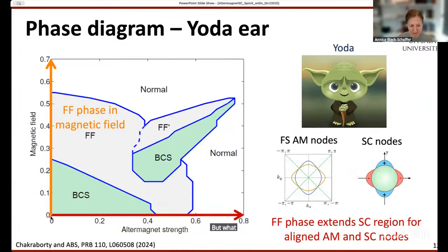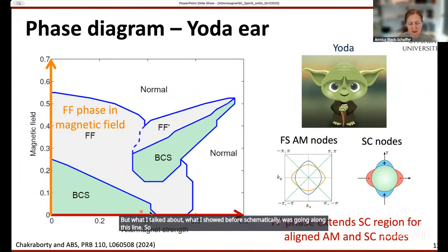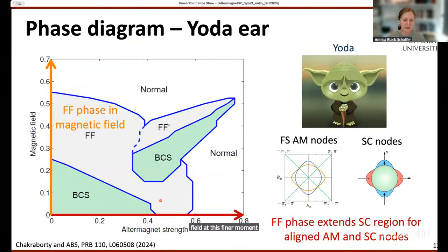But what I showed before schematically was going along this line. So here I go from a BCS to a FF state and then normal. And you see this FF state is actually connected. So here I actually managed to get this FF state, this finite momentum superconducting state, without having a magnetic field, by just having the altermagnet.